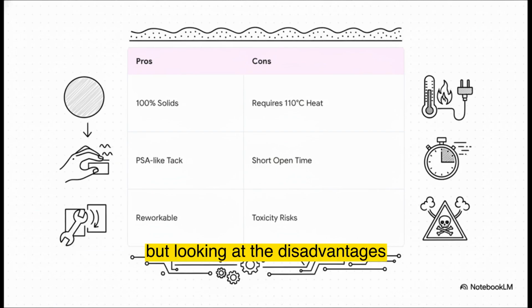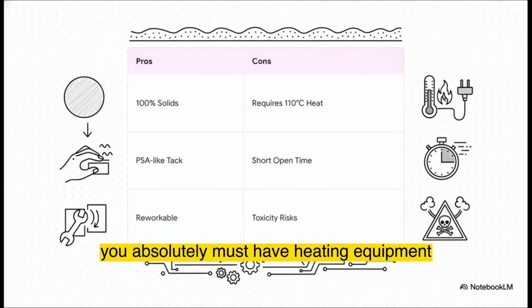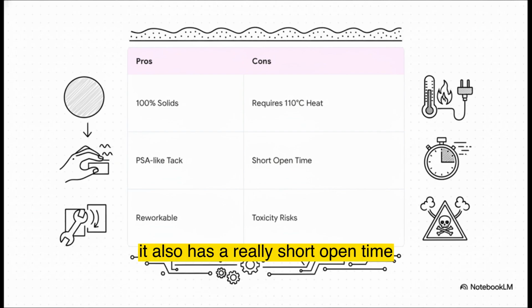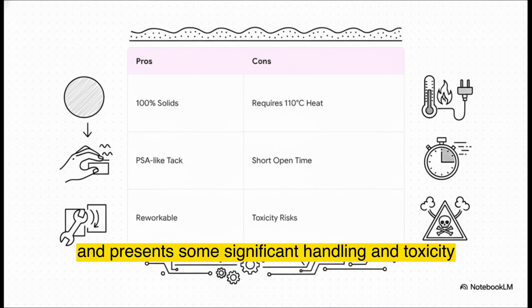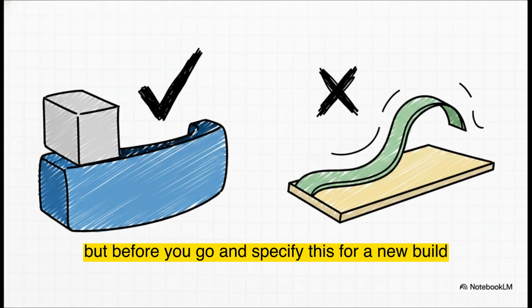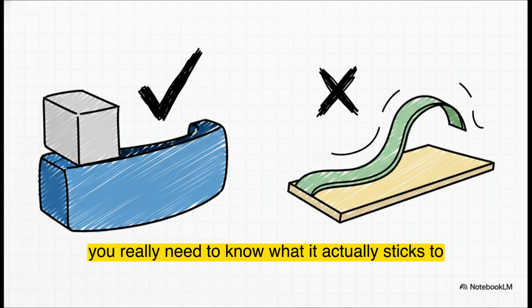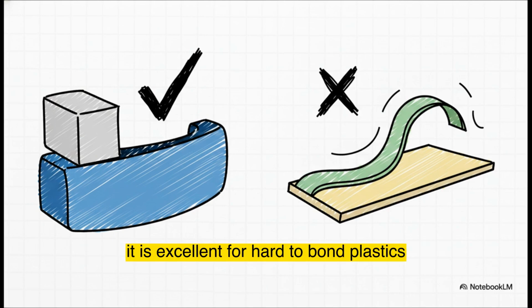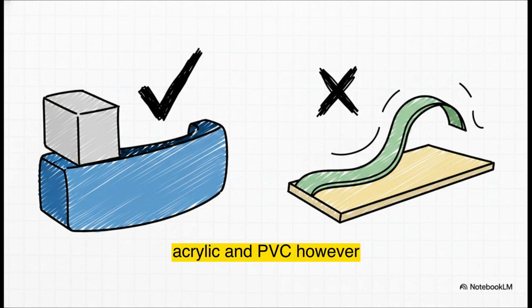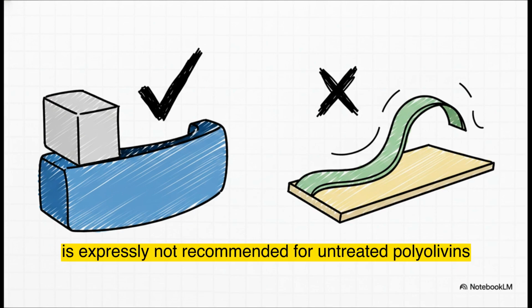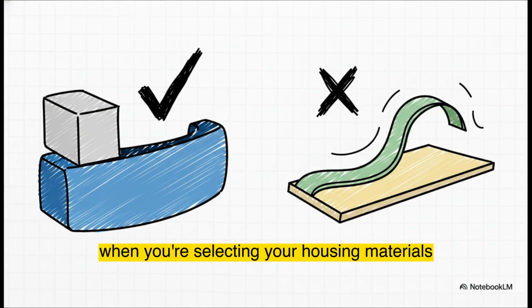But, looking at the disadvantages, you have to be prepared. It demands highly specific equipment. You absolutely must have heating equipment capable of reaching 110 degrees Celsius, which is 230 degrees Fahrenheit. It also has a really short open time and presents some significant handling and toxicity risks, which we're definitely going to cover shortly. But before you go and specify this for a new build, you really need to know what it actually sticks to. It is excellent for hard-to-bond plastics like polycarbonate, ABS, acrylic, and PVC. However, there is a major warning here. The 3M 2665 is expressly not recommended for untreated polyolefins, so keep that in the back of your mind when you're selecting your housing materials.